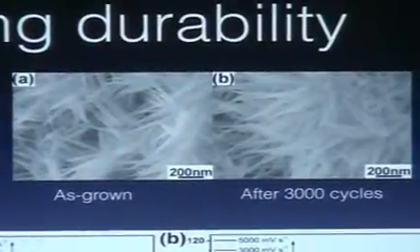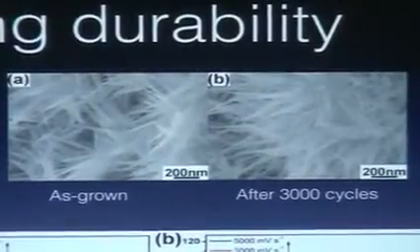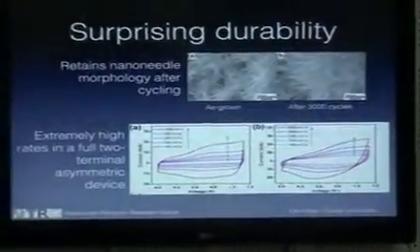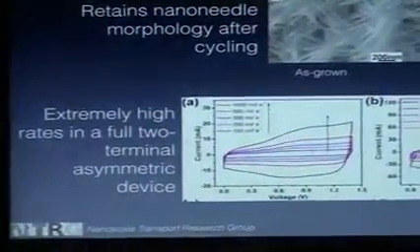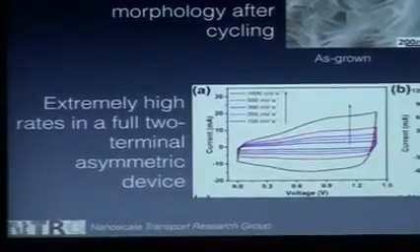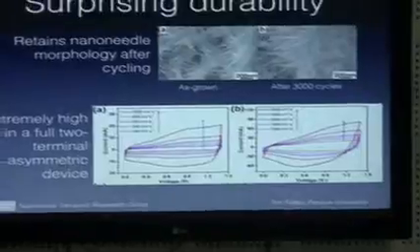So what's happening as these things are reacting and then reacting again upon charging and discharging is that these needles allow for chemical expansion during the charge and discharge cycle, and they have room to do it because they're isolated high aspect ratio structures. Whereas if they were in some sort of a jammed granular configuration, they'd be pushing on each other like a normal battery electrode does, and slowly decrepitating, forming cracks and so forth. But these aren't, right? So I think this is a crucial part. Of course, it also has ultra high surface area. Those nanoneedles have tremendously high surface area relative to their weight.